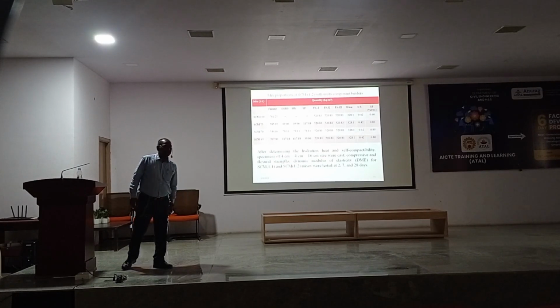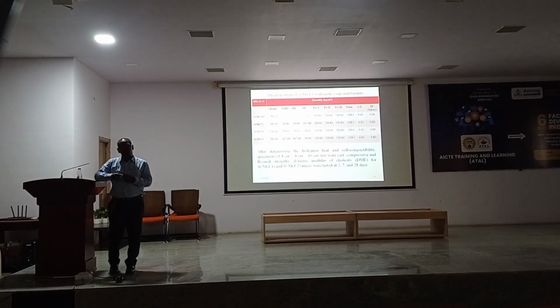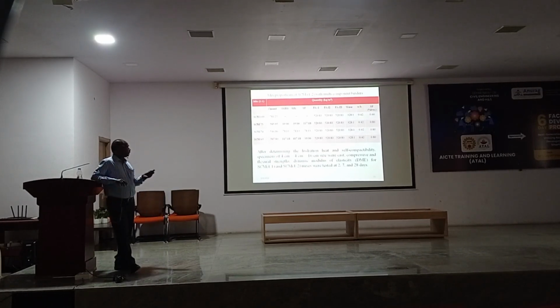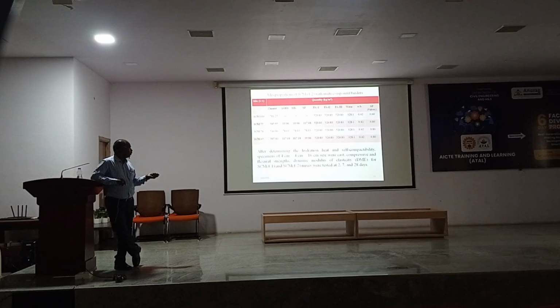Okay, after mixing this, the same specimens, 4 cm by 4 cm by 16 cm, for compressive strength, flexural strength, and dynamic modulus velocity are tested at the age of 2, 7, 28 days. In the last session we conducted at the age of 7, 28, 91. But here 2, 7, 28.